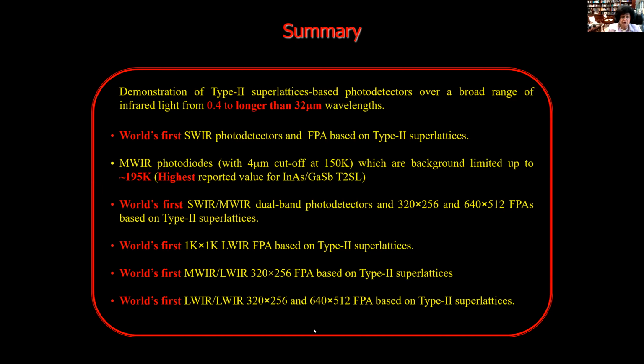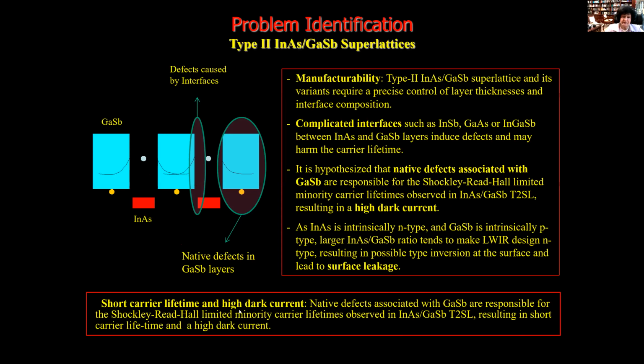We demonstrated type-2 for the short wavelength, mid wavelength, long wavelength, and at the same time different focal planes for the first time, 1K by 1K for the long, and at the same time the mid, short, and all of that. But the problem was that when we make this material, the interface is very important, because we have the gallium antimonide, first of all, with the lattice mismatch, so at the interface, the indium antimonide or the gallium arsenide type, we have to do some engineering in order to have lattice match. That is the one part, and gallium antimonide at the same time is always p-type, so there is a kind of defect that we should get rid of, and that creates the problem again, high dark current in this material.